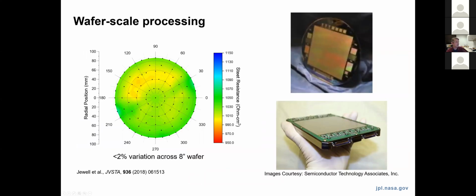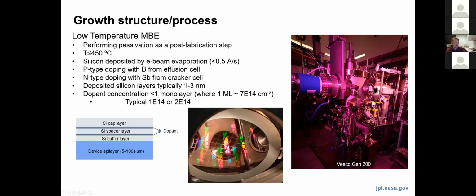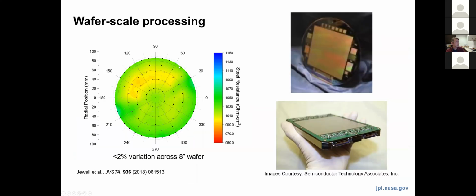This is a wafer scale process, as you saw on the last slide. This was an image of a wafer through a viewport on the MBE tool that we use. We can perform this process on up to 8-inch wafers, which is compatible with a lot of the CMOS fabs these days. And we've demonstrated really nice uniformity across these large areas. And that's becoming more and more important for larger and larger area detectors, some of which now are essentially consuming the entire area of a 6-inch or 8-inch silicon wafer.